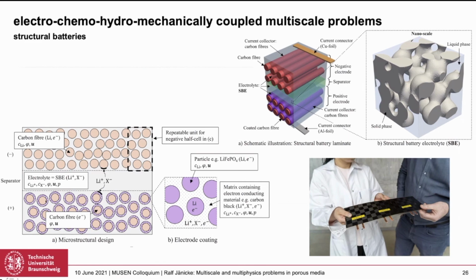So one part of the electrodes of the fiber is coated by lithium-rich particles. In that case, the fiber is acting as a collector of the current, and the electrochemical process happens here in this coating, where lithium particles are set free if the potential is like this. Here's the separator in between, and here are the second electrode, the negative electrode, where lithium ions are intercalated. That means that they enter the carbon black, and they take interstitial places in this carbon black structure.